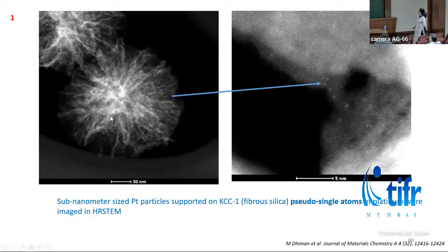Now here are examples of samples imaged using TEM. These are the KCC or fibrous silica samples prepared in Professor Vivek Polshettiwar's lab, and they were loaded with platinum particles. So these bright spots which you see, they are platinum particles, and when we magnified the region here, we could see fine bright spots. These are pseudo platinum single atoms.